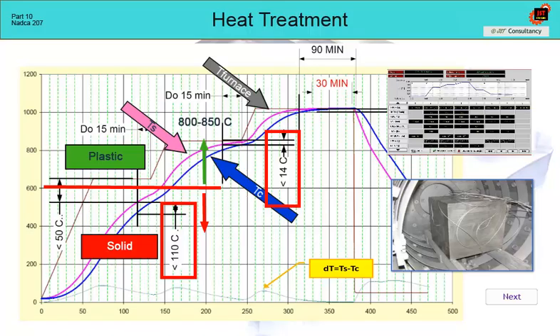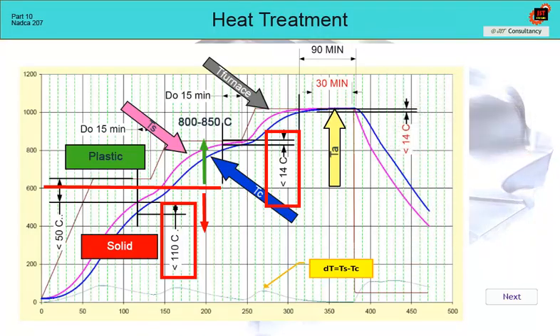The austenitizing temperature and time are also precisely defined in NADCA 207. From the point of view of the result, this is an important part of the process, which must not be too short, because the material would not be fully heated up, and the quenched structure would be significantly heterogeneous, and it must not be too long, because the austenite grain could become coarsened. In both cases with a negative impact on the impact strength values. Therefore, the following conditions apply to austenitizing.